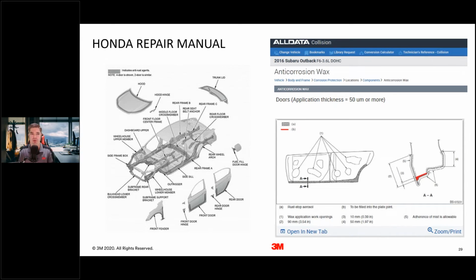And what's important to point out here is if it has to stick to those sidewalls and you have to have a certain amount of mil build, commonly I'll hear technicians say, I use brand XYZ because I know I've got enough cavity wax in when it's running out all over the floor. Then I know I've got enough inside. But then my question always is, if it's on the floor, what was left inside the vehicle? If 75% of what I put into the vehicle is now laying on the floor and there's only 25% left, is there enough mil build on those surfaces to protect it?